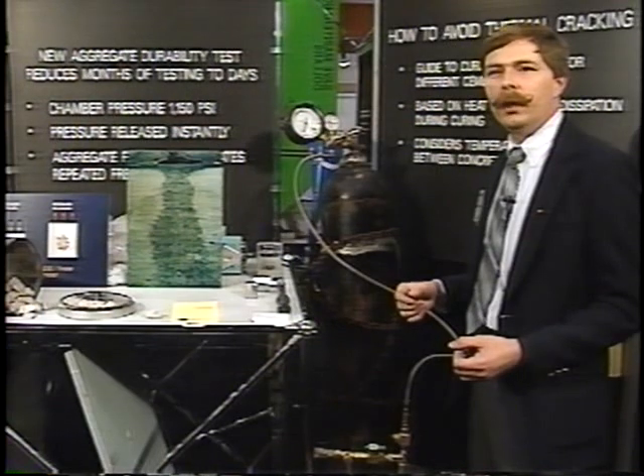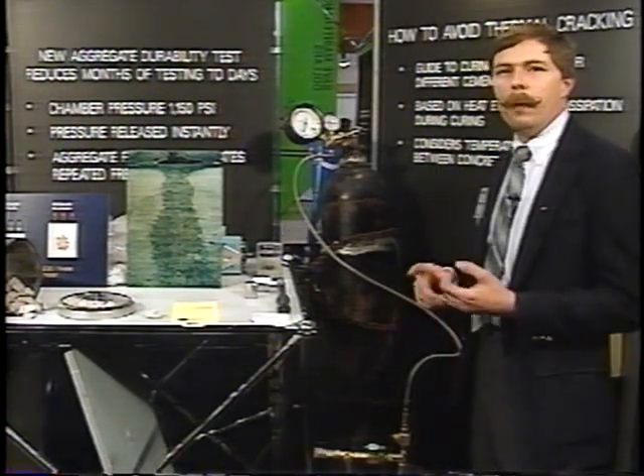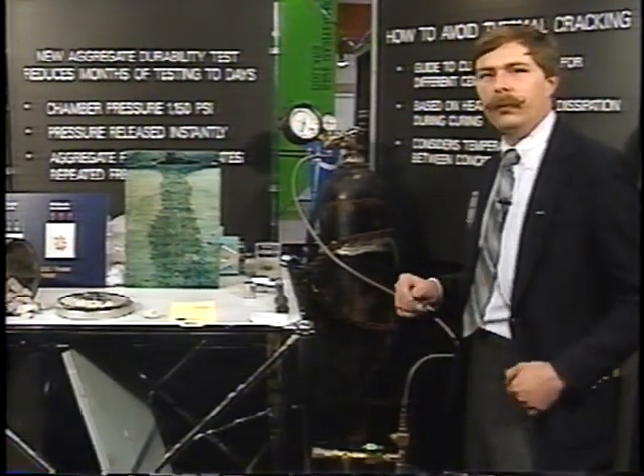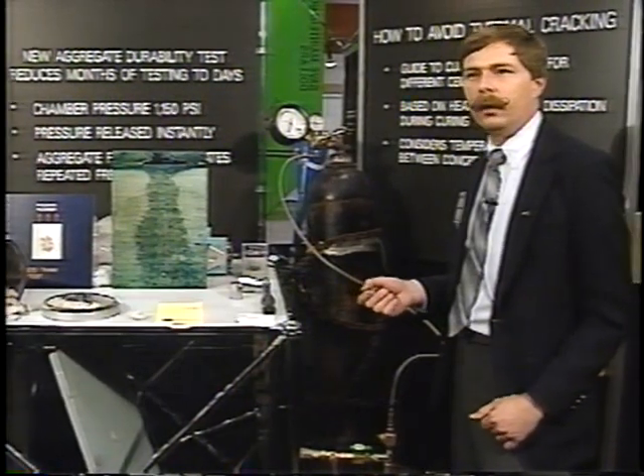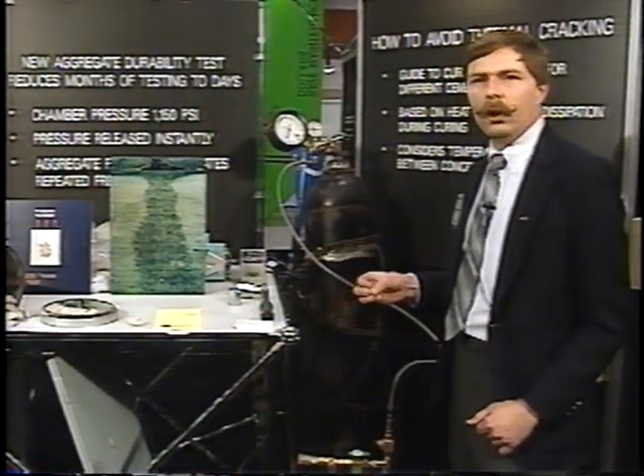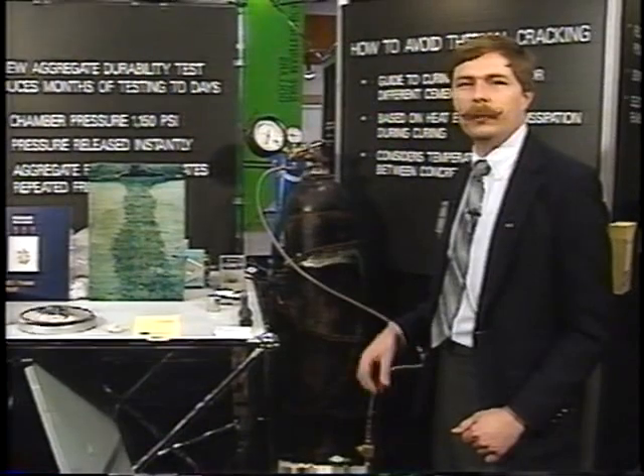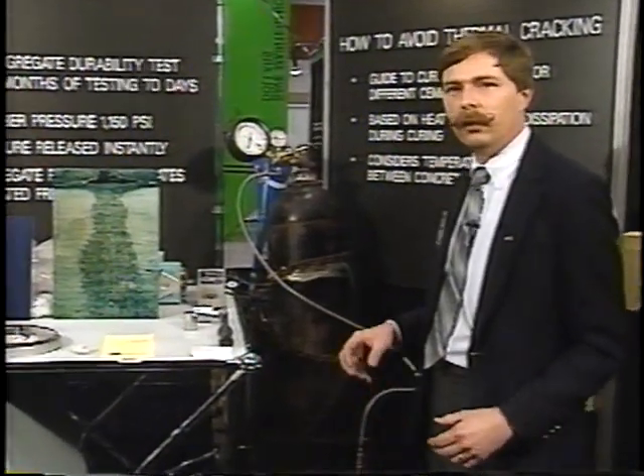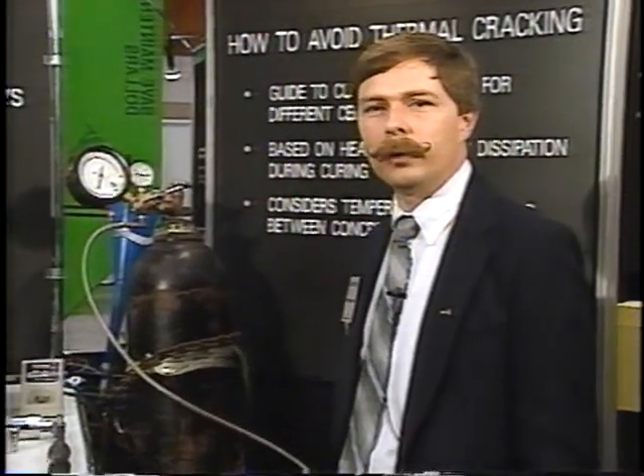We do that for 5 days for a total of 50 cycles. A bad aggregate would probably have 10% or more fracturing at the end of the 50 cycles. A good aggregate would probably have 5% or less. So we can then tell the difference between good and bad aggregates by the percentage of fracturing.